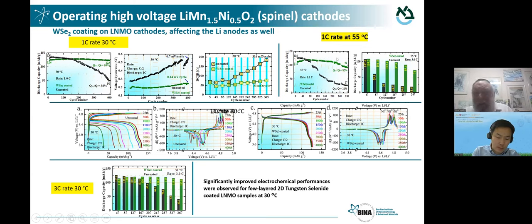And this stabilization is maintained also at elevated temperature. So here you have another comparison at relatively high rates at 55 degrees C. Look at the green histograms compared to the black histogram. So the stabilization is impressive. And this is because we form a buffer zone. This buffer zone, first of all, mitigates any possible side reactions between the negative, the positive, and the electrolyte solution. Also, it mitigates the dissolution of transition metals, which is detrimental to both the positive and the negative electrodes. And the result is stabilization.